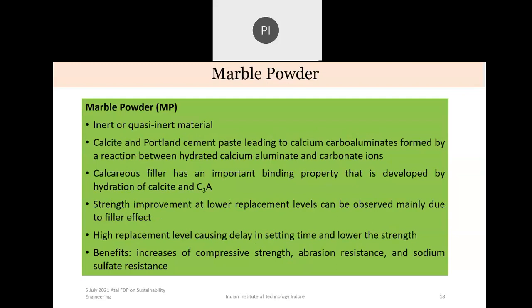Next supplementary cementitious material is marble powder. So it's basically an inert or quasi-inert material, a filler for some time, but later on people realized that it can have certain cementitious properties also. It can be used as a supplementary cementitious material also. So the calcite and Portland cement pastes lead to calcium carboaluminates, which are formed by a reaction between hydrated calcium aluminate and carbonate ions. And this calcareous filler has an important binding property, which is developed by hydration of calcite and C3A. And strength improvement at lower replacement level can be observed mainly due to the filler effect. At higher replacement levels, they cause delay in setting time and lower the strength. The benefits are it increases the compressive strength, abrasion resistance, and sodium sulfate resistance.